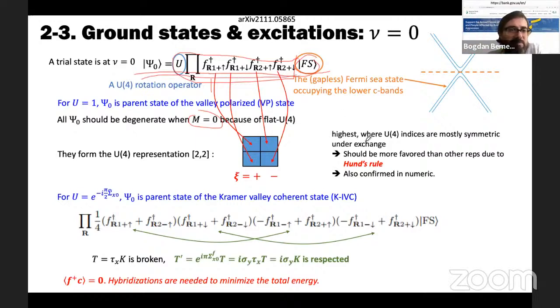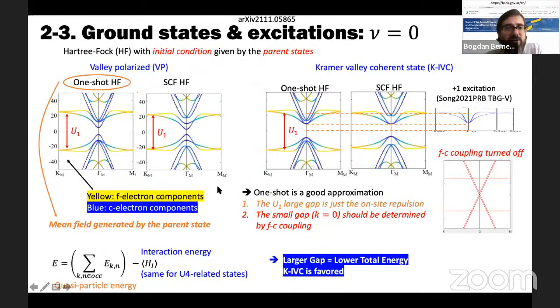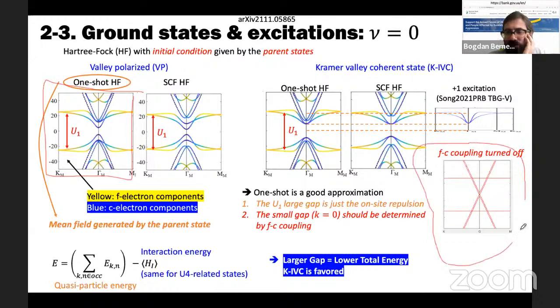So you take this trial state and you run one-shot Hartree-Fock, which turns out to be amazingly consistent with self-consistent Hartree-Fock. And one-shot Hartree-Fock can be done analytically. So what happens here is very easy to understand. Let's look at this plot. Basically, by the same token, you get all the interacting states. Let's start with the f-electron to c-electron coupling turned off, but now fix the filling by occupying f-electrons, the heavy electrons, to minimize Coulomb. That moves the f-electron bands up and down. Okay, it moves them like this.